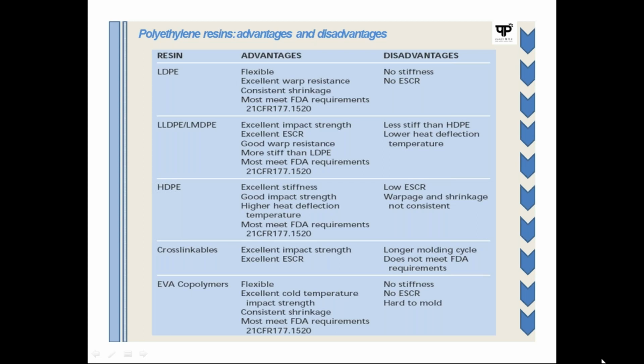Further, you can add one more into this, HMHDPE, which is a further high-end material among this polyethylene group. But if you want to further increase the strength of the polyethylene material, you can go for cross-linking. But there is a restriction: if you go for cross-linking, then you cannot make a very good flowable material. So in this case there are limitations as far as the size of the product is concerned. The next material is EVA, which is normally used for toys and softer materials. It is a more flexible material, with excellent resistance to cold temperature, and consistent as far as shrinkage is concerned.